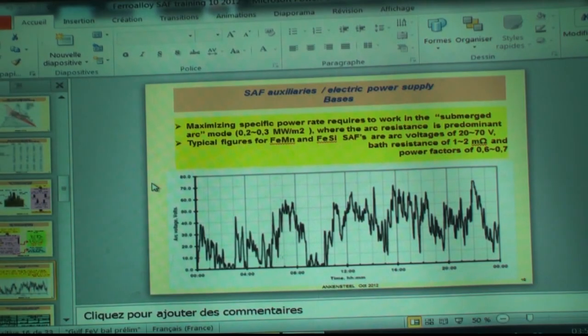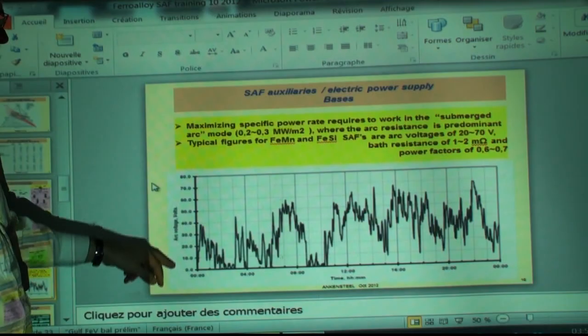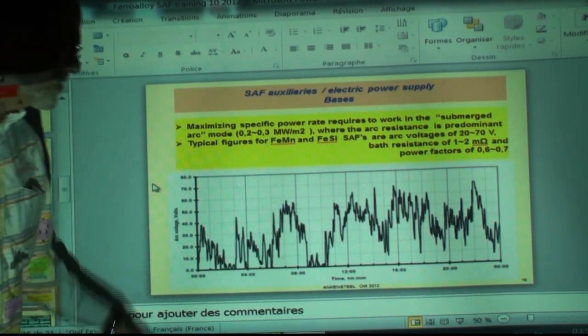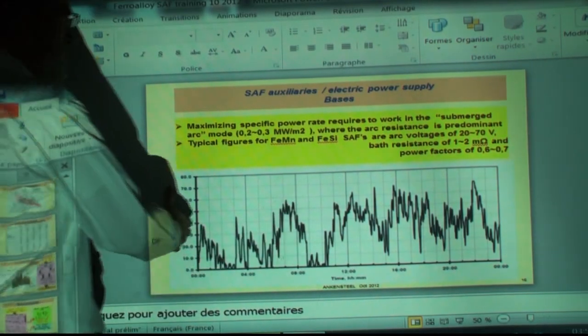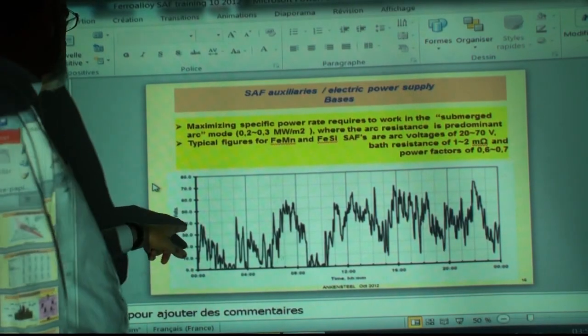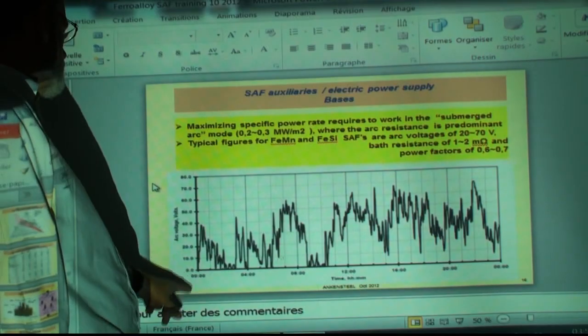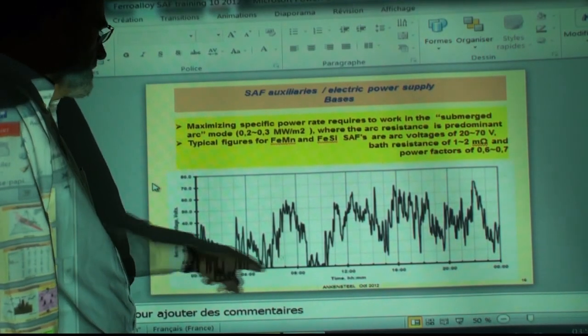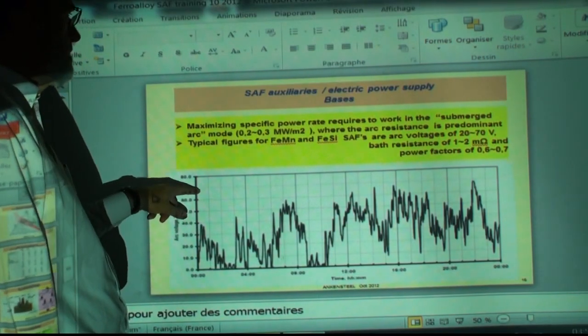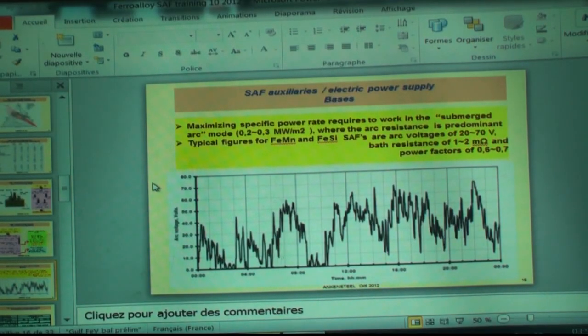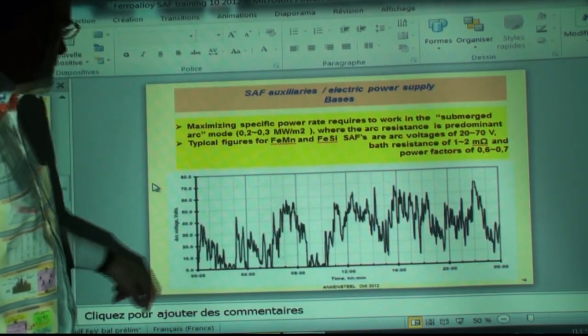The typical arc voltage that you can obtain in ferromanganese and ferrosilicon, but also ferrochromium furnaces, are arcs of 20 to 70 volt. This is typical, and this is arc voltage measured on a ferrosilicon furnace over time. You see, of course, it may vary, but in average it is 30 to 40, and the fluctuations are mostly between 20 and 70 volt. The time scale is hours: 4 hours, 8 hours, 12 hours.